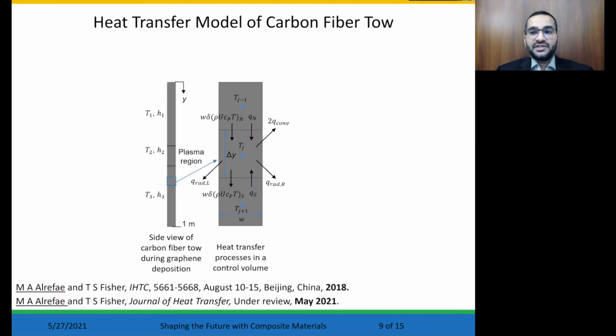Here, we developed a one-dimensional heat transfer model along the tow length, considering a 1 meter long carbon fiber tow. The substrate was divided into 3 regions: pre-plasma region, plasma region, and post-plasma region. Each region has its convective heat transfer coefficient and gas temperature, which was measured during the experiment. We developed a numerical model considering convective and radiative heat transfer from the tow to the gas and the chamber wall, respectively. Also, conduction and advection in the tow were included in the model.